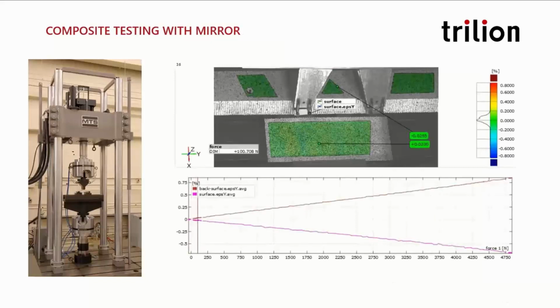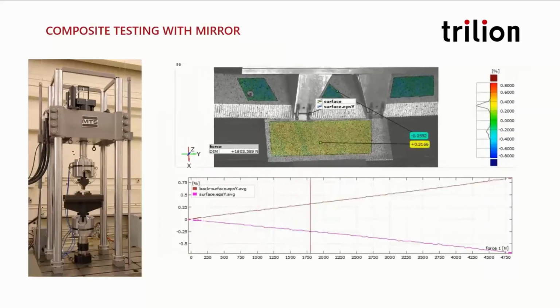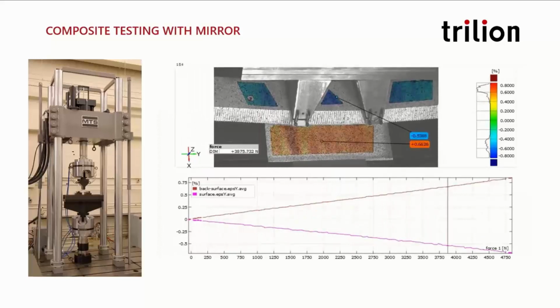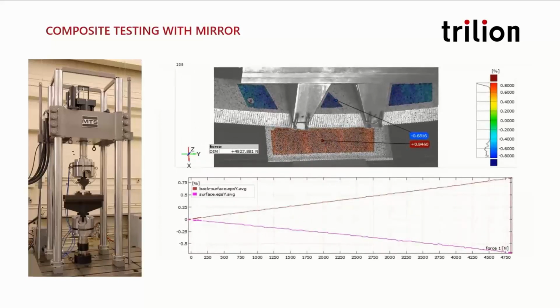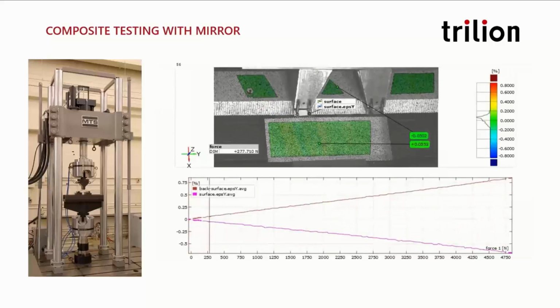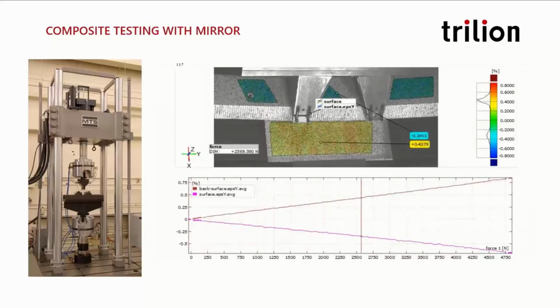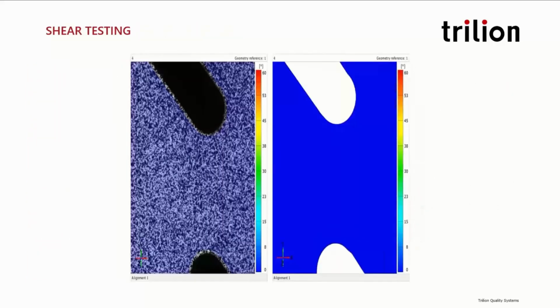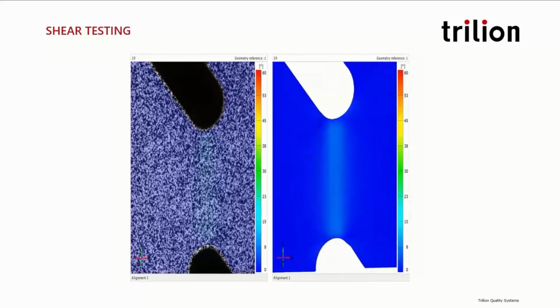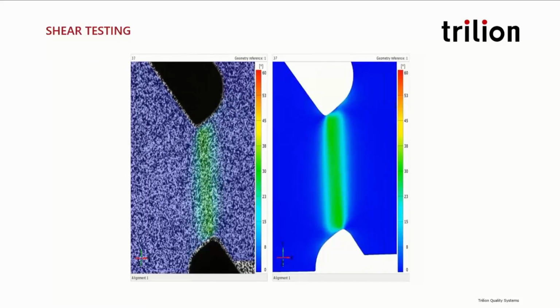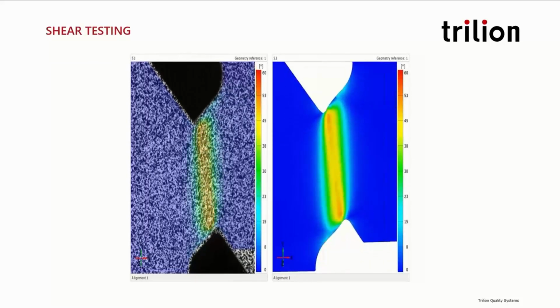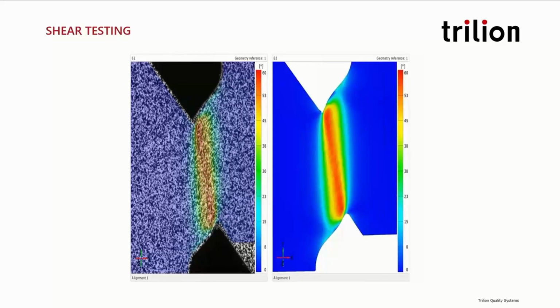Typical example here, in a 4-point bend test, we see, actually just using a mirror, our system doesn't care, you see both the tensile and compression sides of this specimen in a very simple way. And again, just a very simple setup. You get into shear testing, and this becomes a really powerful feature of the technology, because shear is typically how one plate is moving relative to the other, and you're going to make assumptions about the shear. But here we get hundreds of measurement points in through the shear region to truly understand how shear works.